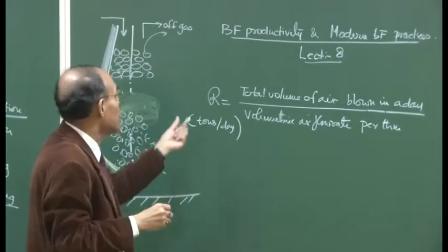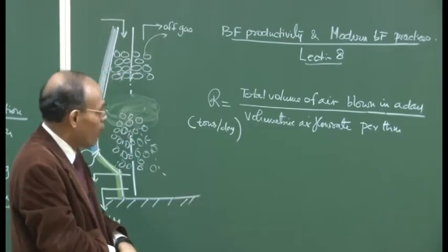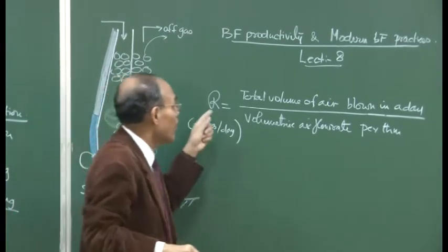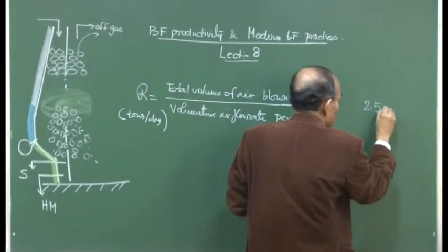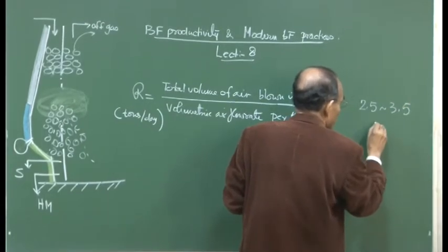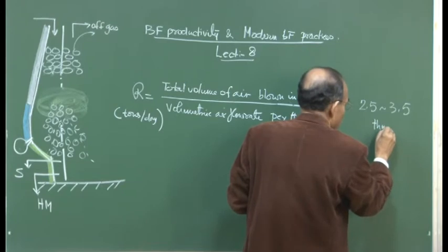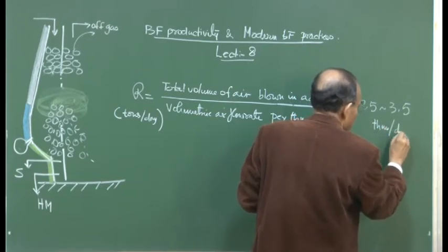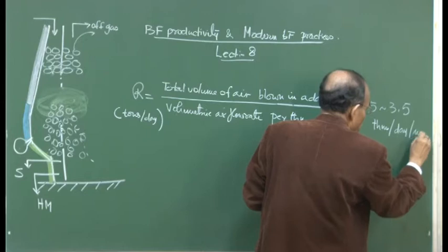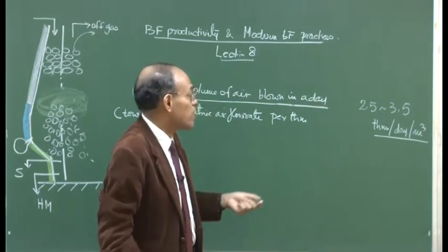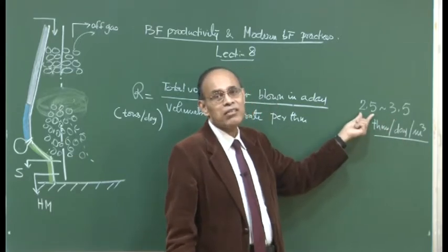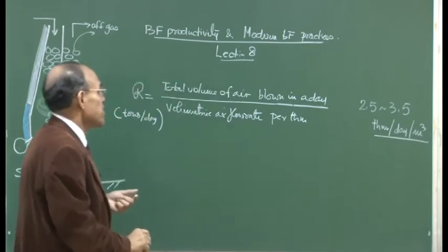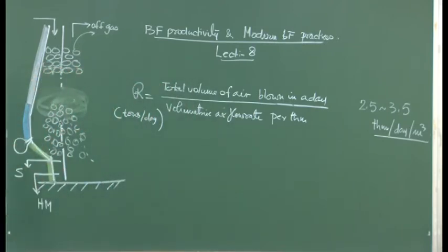What is more important to achieve a good value of R — high productivity — is that the productivity of modern blast furnaces runs something like 2.5 to 3.5 tons per meter cube per day. Very advanced countries with good blast furnace practices achieve about 3.5; inferior blast furnace production is around 2.5 to 2.6. That is the range of R values seen for blast furnaces throughout the world.